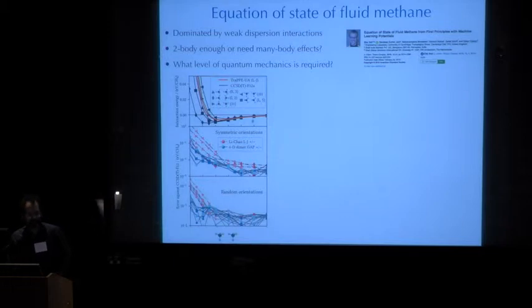And this red curve is the simplest potential that people have been using to describe it. It's some sort of crude rotational average. But of course, one can make that more accurate. So, still an empirical model, this red one, and what I'm showing here is the error. Note the scale here goes up to say 0.1, and here the errors go from 10 to the minus 5, and these errors on the red model are significantly larger, and we can make the blue model, which is what we made, where the errors are down to 10 to the minus 3. So we can fit these black curves very, very accurately.